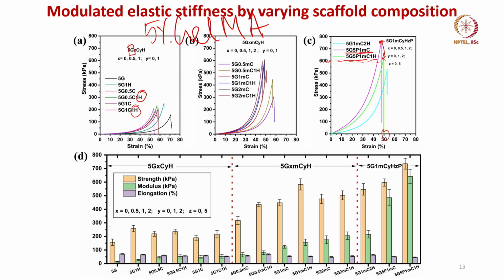Now, this comparison is much valid here, and in this bottom plot a lot of data has been plotted. One is the strength, one is the modulus. Modulus is typically measured from the most linear part in the initial loading of the hydrogel scaffolds. Then also elongation, percentage strain, maximum strain. Percentage strain wise there is not much difference. Typically the strength value remains moderate when you use 5% GelMA with carboxymethyl cellulose and hydroxyapatite, like 5G, 5G1H. So, strength increased a little bit, 5G 0.5C, 5G 0.5C 1H, a very small increase. The modulus also increased a little bit.